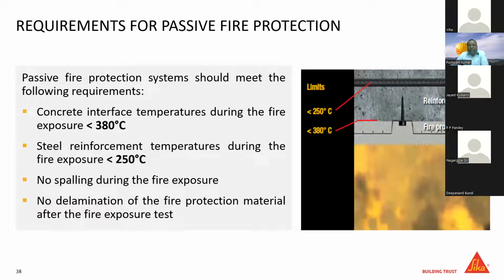There are clear guidelines that, in case we have to strengthen or protect a building structure or any RCC structure from fire, the concrete interface temperature should not go beyond 380 °C, and the steel reinforcement inside the RCC structure should not cross 250 °C. On the right-hand side, you can see the photograph. This is the RCC section wherein within your cover you have the reinforcement, and on top you have the fire protection mortar. Because of this fire protection mortar, the interface temperature between the concrete and the fire protection mortar should not go more than 380 °C, and the reinforcement embedded inside the concrete should not increase beyond 250 °C.